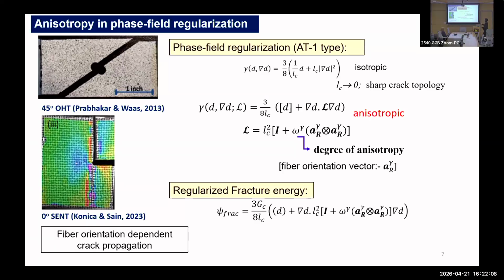Okay. So with this framework, the important point, again bringing back those experimental pictures, is that the crack is heavily fiber orientation dependent. I'm pulling both of these specimens under tensile loading, but in one case the loading is parallel to the fiber direction, and in the other the fiber is at a 45-degree angle, and the crack propagation happens parallel to the fiber direction. So how do we incorporate this anisotropy in the fracture?